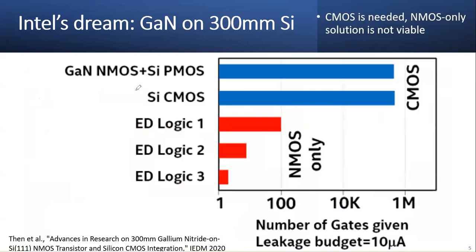And you could see that they also found out that you need a CMOS. NMOS only is not good enough. With NMOS only, the number of gates you can do will be a lot fewer. You really need a CMOS to be commercially viable, so as to compete not directly with silicon CMOS, but in the SoC field they are interested in. This is a good companion to the silicon CMOS they're doing. And of course, it's not an easy thing, right?